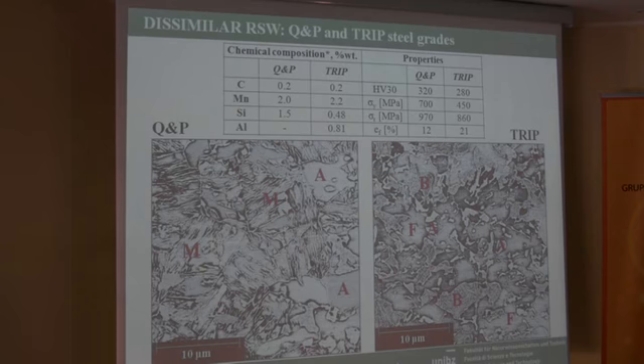And here you can see in better detail the microstructures of the two examined steels, particularly the quenching and partitioning steel. As said before, we have martensite and austenite. Instead, in the microstructure of the other steel, we have ferrite, which is the matrix, some bainite phases, and then we have some austenite.